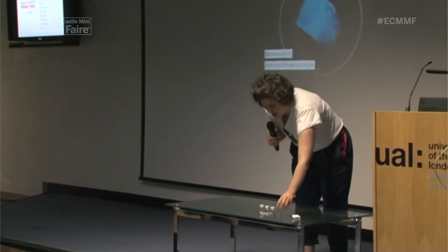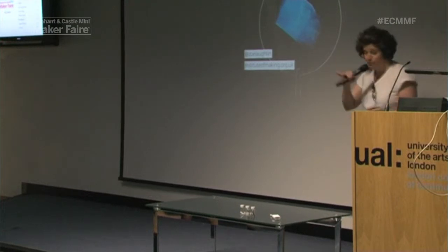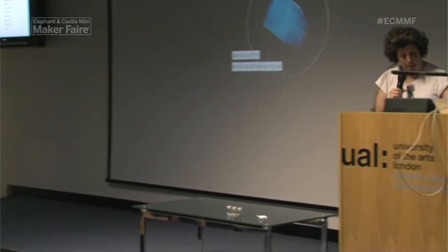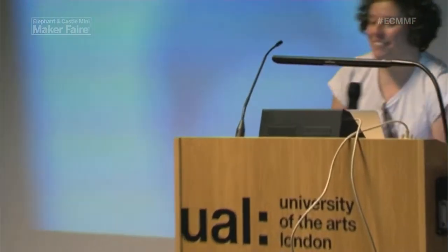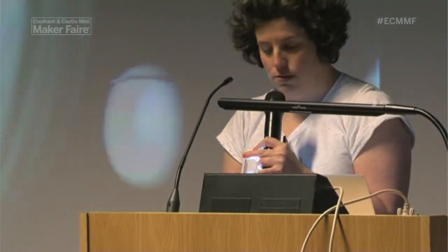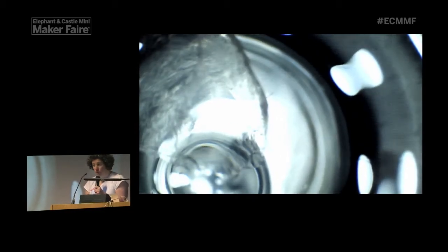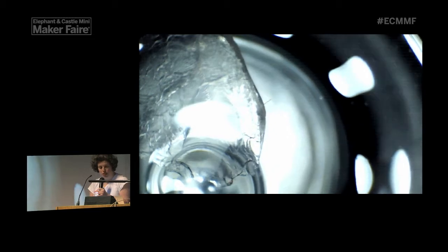This one? So this is some aerogel, of the picture of which you can see here. And this material is dropped on the floor. This material is designed by NASA for catching stardust. At the time it was made, it was the lightest solid in the world. It's 99.8% air, so only 0.2% of it is the stuff. And the stuff in this case is silica, so it's a kind of glass.